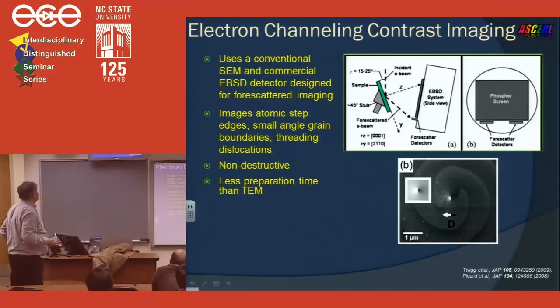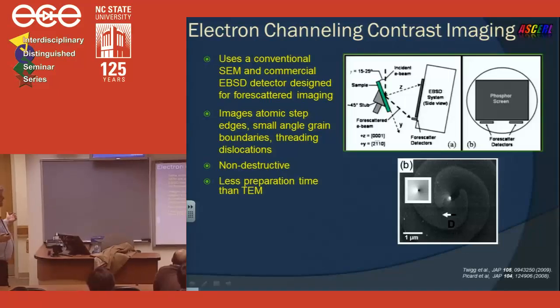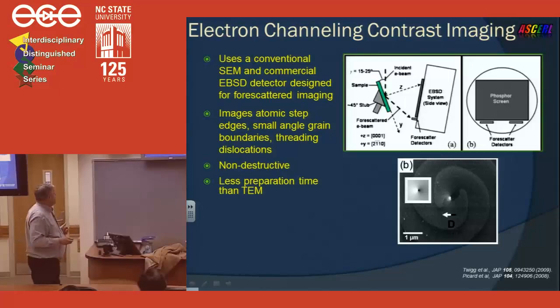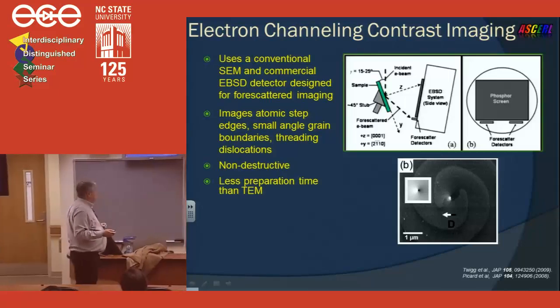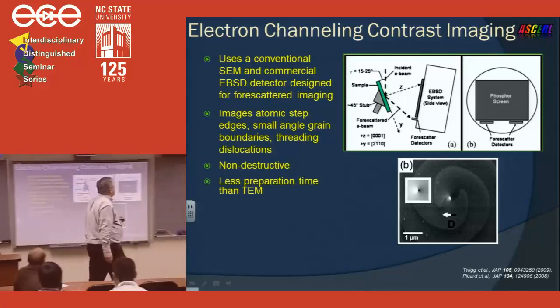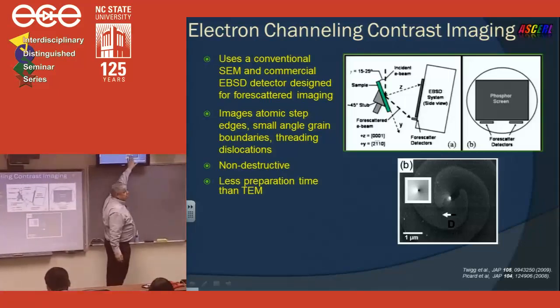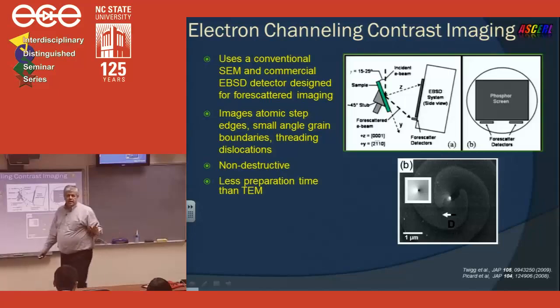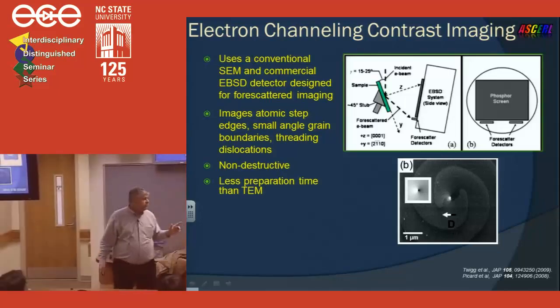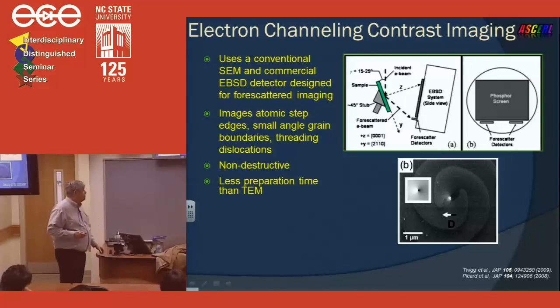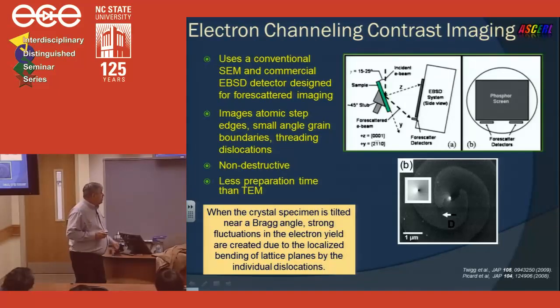And the way we're going to do this is we're going to use electron channeling contrast imaging. So if you have an SEM with some really good forescattering detectors, you could do this here too. And ECCI is of great value because it allows you to see almost three-dimensionally on the flat SEM surface. And so in this particular instance, you can see this little divot here, and I'm going to demonstrate to you that that's a threading screw dislocation. And so you can see dislocations in SEM images. And the way we're going to do that is we're going to take our sample and we're going to carefully march it through Bragg angles, and you will see the change in the electron channeling contrast imaging.